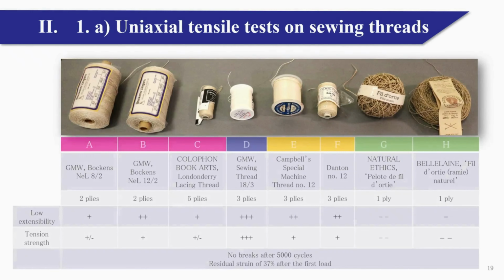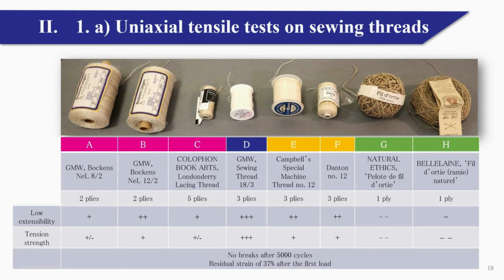The results for the sewing thread make it possible to classify them according to extensibility and tensile strength. The results of the cyclic uniaxial tension test showed no breakage after 5,000 cycles. Consequently, the breaks sometimes observed during sewing seem to be caused more by abrasion of the thread on the parchment folios and sewing support than by repeated traction.